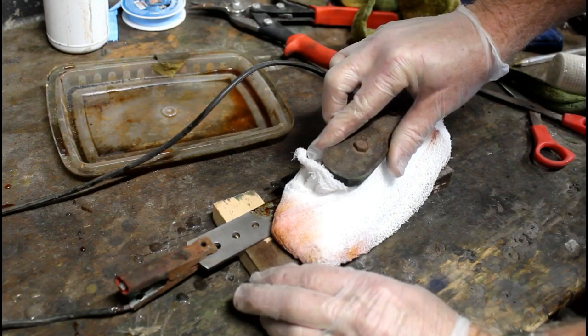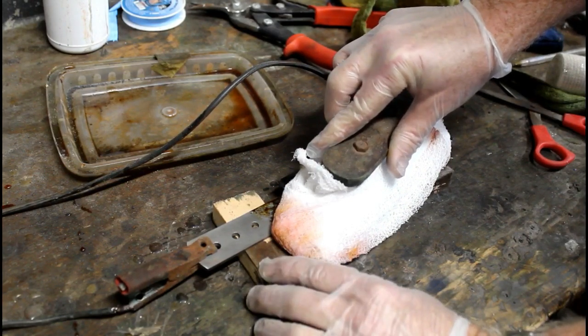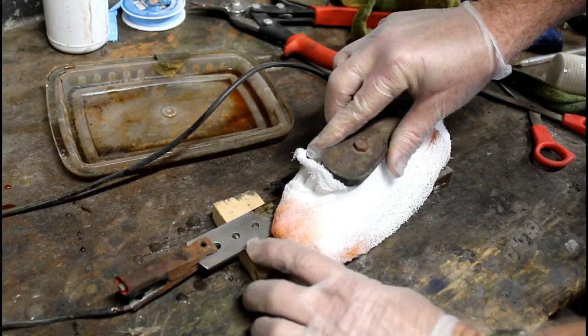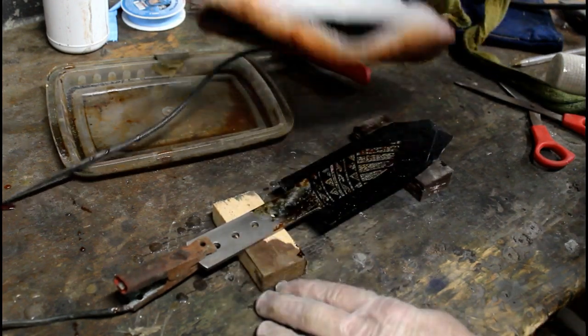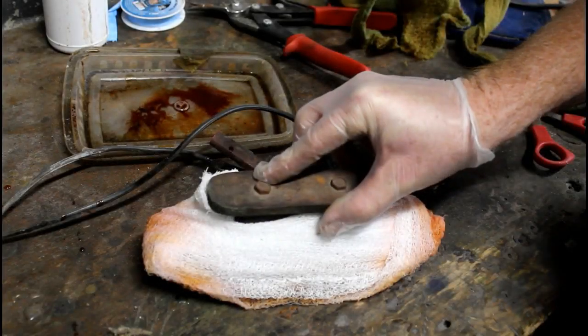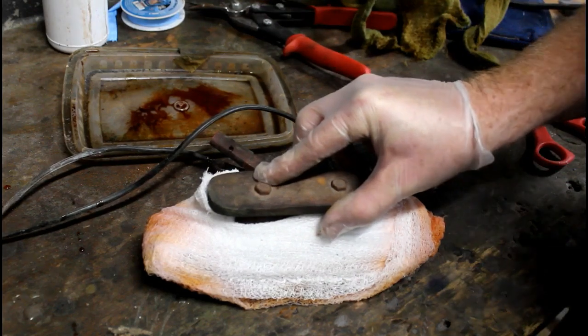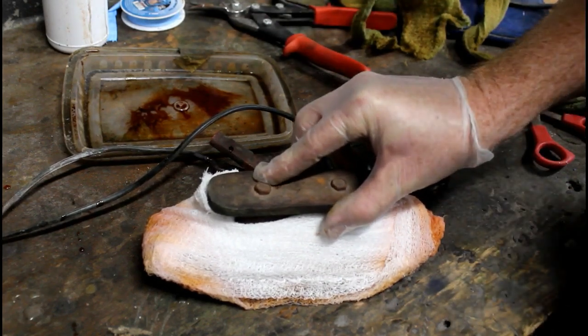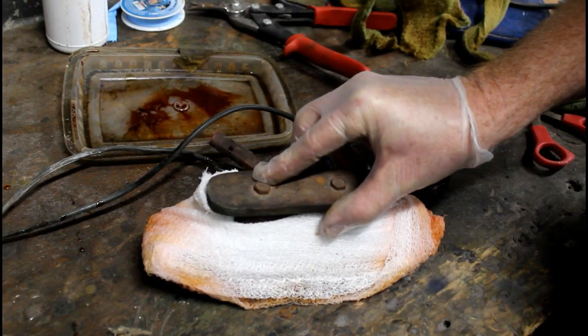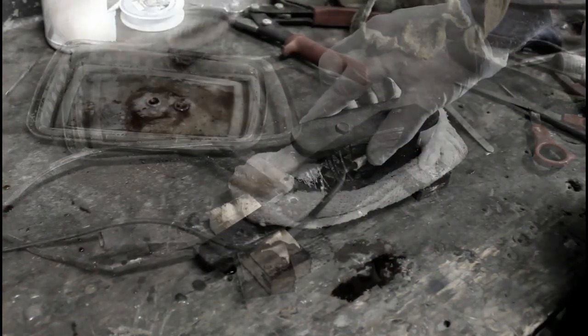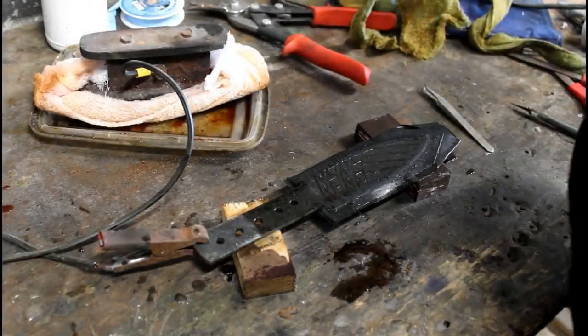If you did, you'd really chance that self-adhesive vinyl losing its adhesion, and then you'd end up with not the best etch. You'd have solution that seeps underneath the vinyl, and it would just look horrible. So you're better off taking your time and doing some cooling in between. Maybe do a minute, in 20 or 30-second increments, and then let it cool a little bit. I also etched the whole handle area, including the sides.